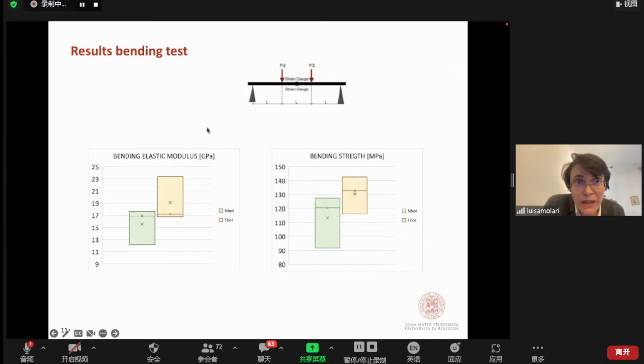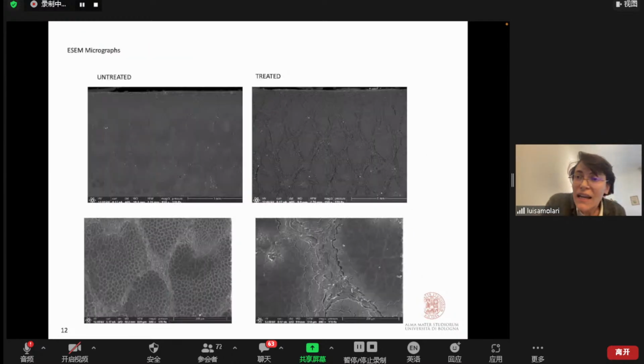For the bending test, we have only the bottom part, because we did the test only for this part of the culm. And what we see is again more or less the same behavior in stiffness and in strength. For the specimens after the bending test, we did micrographs, micro pictures with the SEM, with the microscopy,